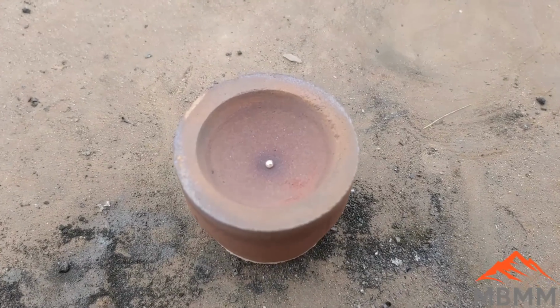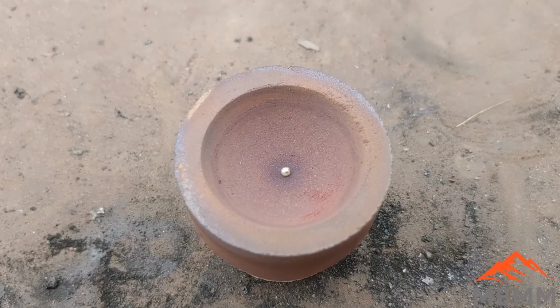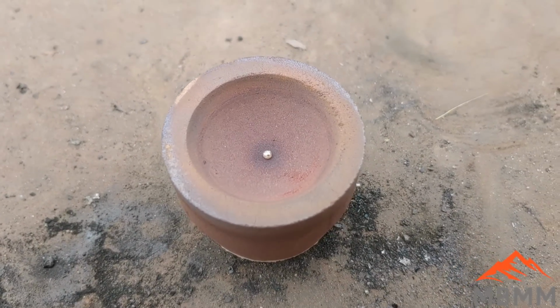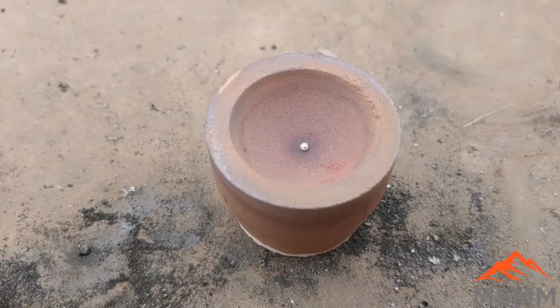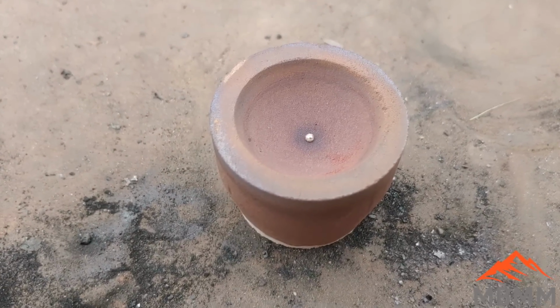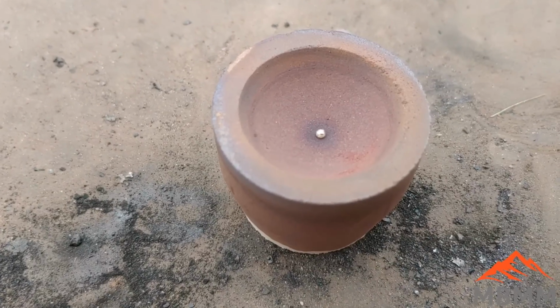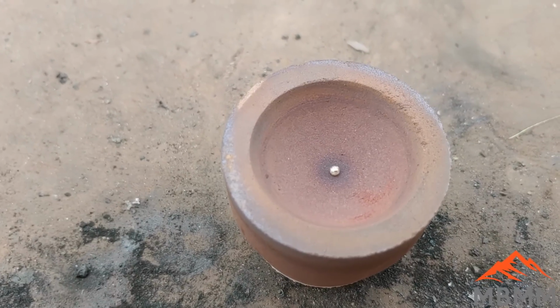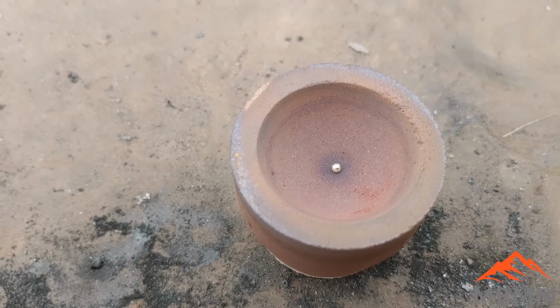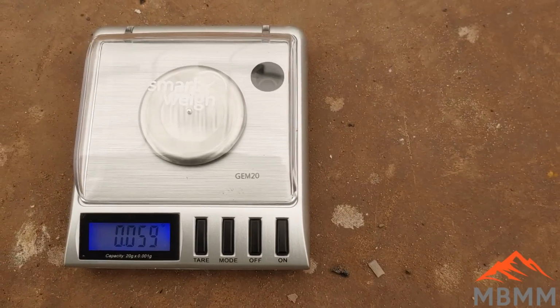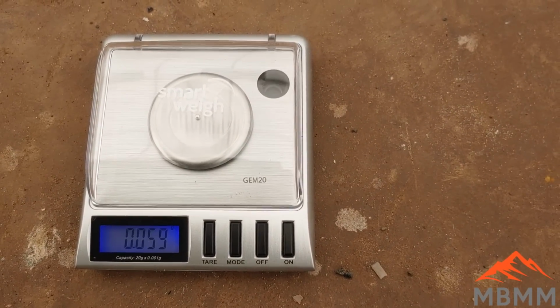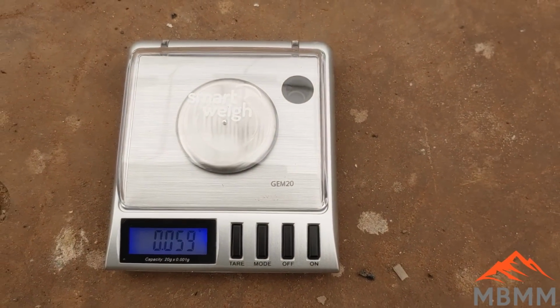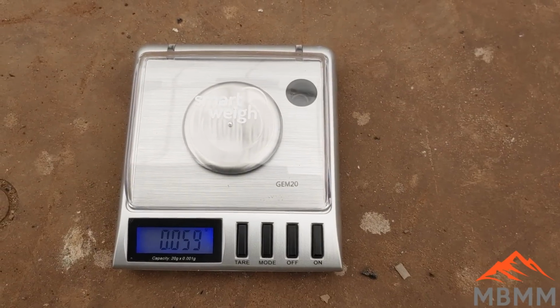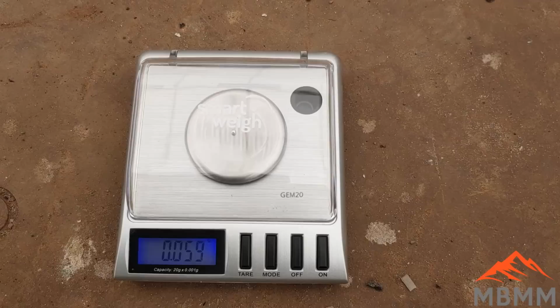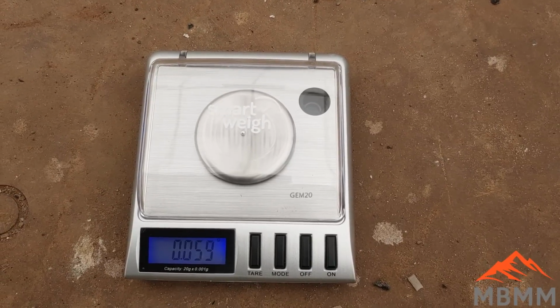And there's our little bead from our first 200 grams of matte. And it's a little bit yellow, so it's probably in that 60 to 70% gold range. But that's what we lost from 200 grams of matte. 0.059 grams. And it's probably about half gold and half silver, maybe a little bit more gold. So we probably got 0.03 grams of gold and 0.03 grams of silver.